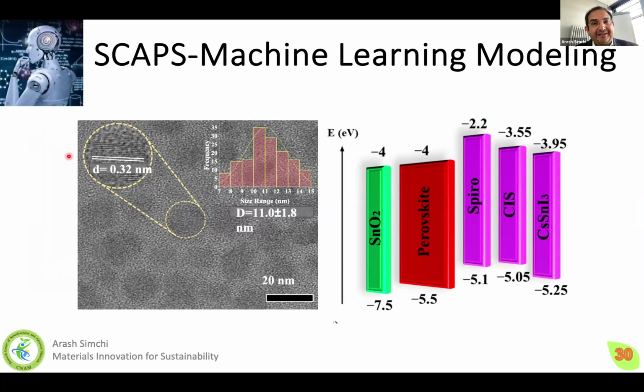I would like to show one example of what we have done in our group to make an efficient solar cell. As I mentioned, we could synthesize very nice colloidal perovskite solar cells, but we didn't want to use very expensive materials, so we designed a solar cell based on tin oxide, perovskite layer, Spiro, and copper indium selenide as a back electrode, as an electron and hole collector on both sides. However, the question is how to optimize the system to reach high efficiency.